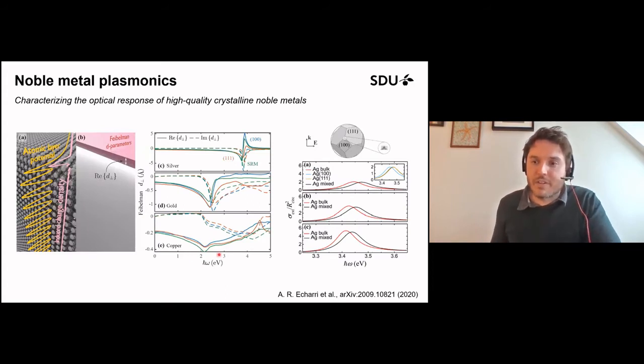So this has kind of triggered us to look at this from the theory side now, and this is a collaboration of us at SDU with my former group at ICFO. And we want to look at how we can characterize the optical response of these high quality crystalline noble metals. And one way to do that is to perform semi-atomistic simulations of these crystalline materials to find their optical response, and from that extract surface response parameters, surface response